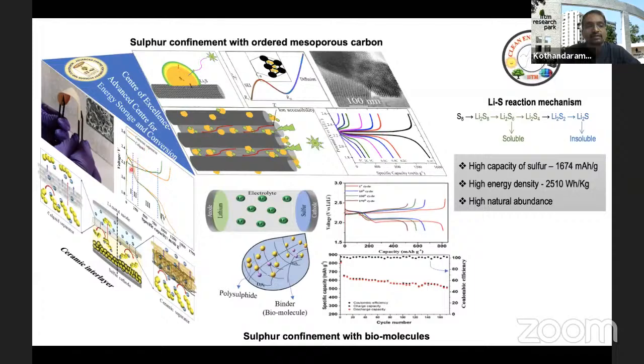And the other approach that we follow is the use of ceramic separators. In case these lithium polysulfides move towards the anode, the ceramic separator placed between the anode and cathode absorbs these polysulfides, thereby protecting your anode from capacity loss. So like that, there are many approaches that we follow as part of this lithium sulfur program in this center.